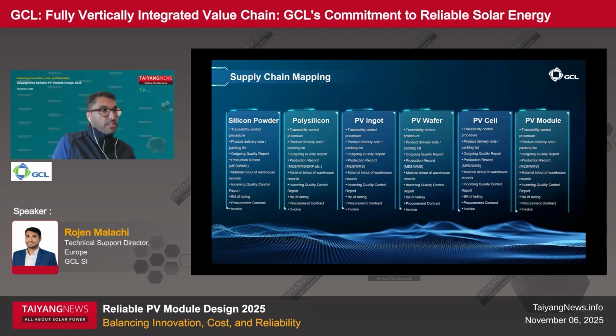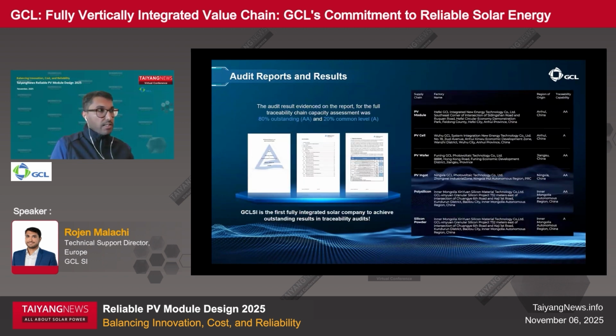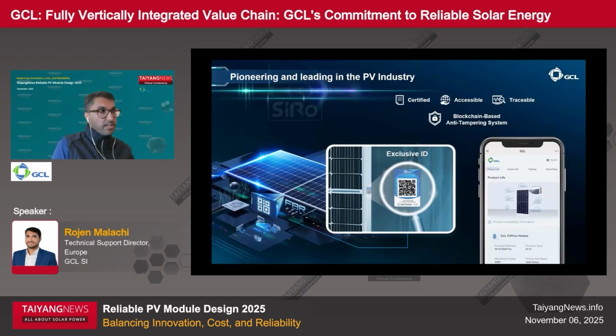Full traceability means every module can be traced back through the silicon batch, wafer, cell lot, production line, test data, and field deployment data. This supports reliability, analytics, and transparent warranty claims. We want to highlight that these are not just data that GCL maintains for supply chain mapping, but have been independently verified by an independent agency, TÜV Rheinland in this case. And these are the results of the audit from TÜV Rheinland regarding traceability. As you can see, it's around 80% with a AA rating and 20% with an A. So this highlights a level of transparency in GCL's supply chain.